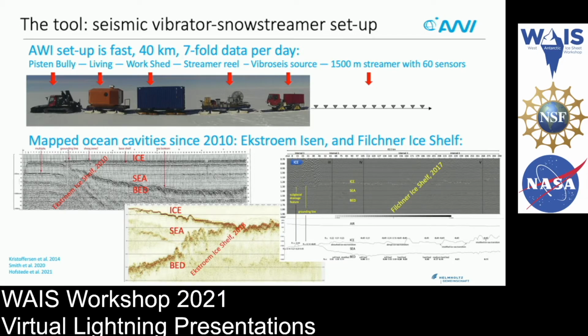We pull the vibrator and snow streamer by Pistenbully and can take a record every 30 seconds. Like this, we can easily collect 7-fold data over a 40-kilometer transect per day. AWI has done this at several ice shelves, as shown below, with good results.